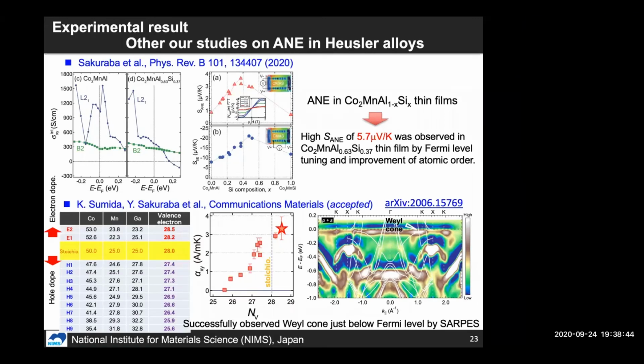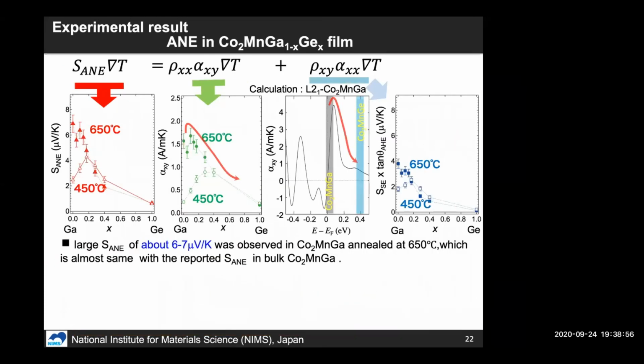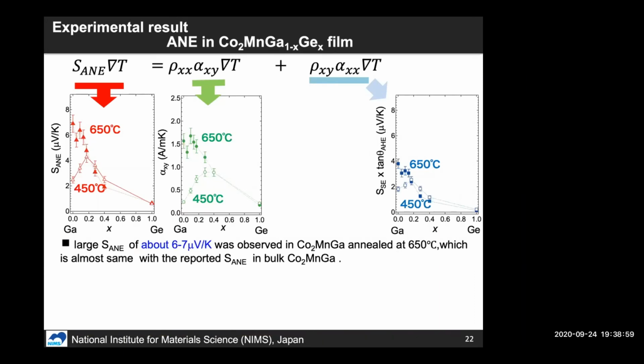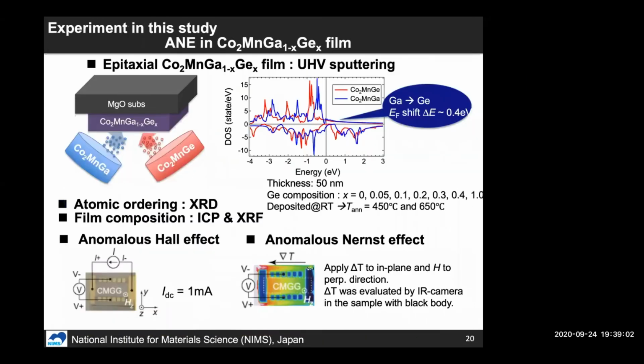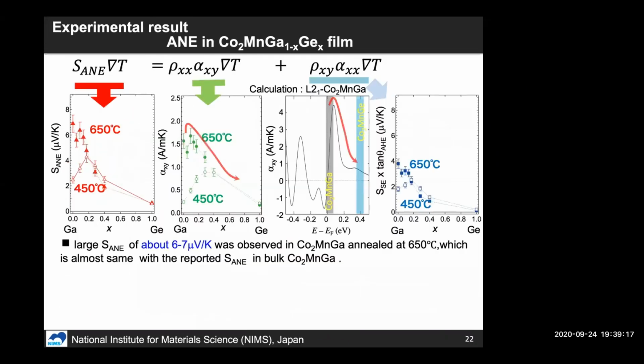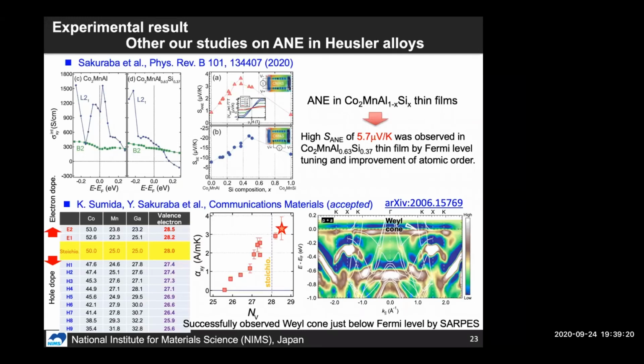So another thing I was curious about: you mentioned the calculation of alpha xy. When you're comparing with your data, because of the L21 to B2 ordering, there might be a shift in the Fermi level. Could you also calculate for the B2 ordering and how much lower the alpha xy will go, because you clearly have B2 ordering in your film? So how much does the alpha xy coefficient actually change? In that sense, if someone can really grow the true L21 material, how much improvement in the Nernst coefficient can one expect?